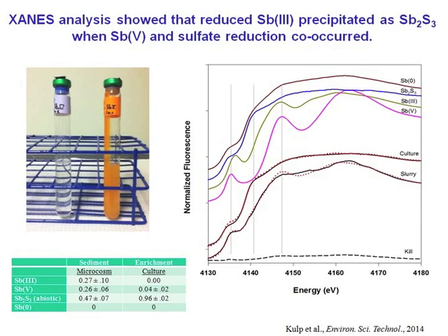And as it turns out, in these particular experiments, we were using a media recipe that contained sulfate. So in addition to antimony 5 reduction, we also had sulfate reduction going on here. And when the antimony 5 reduction occurred in the presence of sulfide, we end up getting this bright orange precipitate, this mineral, which is the mineral stibnite, Sb2S3. So this is an antimony 3 sulfide mineral, and this is biological precipitation of the stibnite. The tube goes from this clear color to being full of this bright orange amorphous stibnite mineral as a result of the microbial reduction.